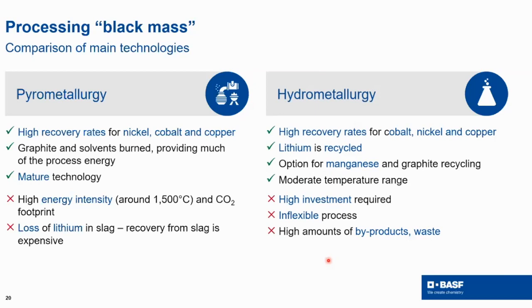Pyrometallurgy is a very mature technology. The black mass or also modules directly are heated up to around 1500 degrees C. Under those conditions, a nice pure alloy of nickel, cobalt, and copper is built. And this alloy can be separated. It's very clean and then can be separated further into the metals. However, the lithium goes into the slag, and part of the manganese goes into the slag. It's more or less lost. Of course, you can extract it again. However, this process is very, very tedious.